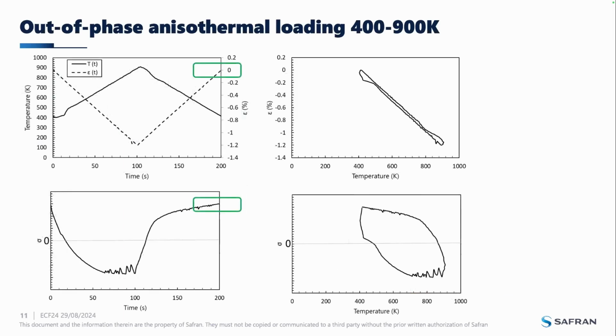So just above, the strain which is imposed on the specimen, you have the stress response, and you can see that just after a few cycles, because of strain hardening, at 0% of mechanical strain, the stress becomes widely positive.